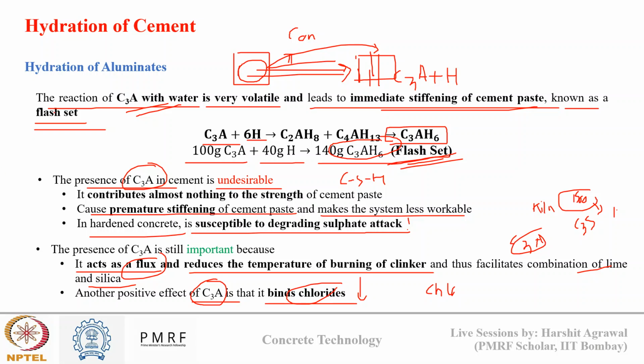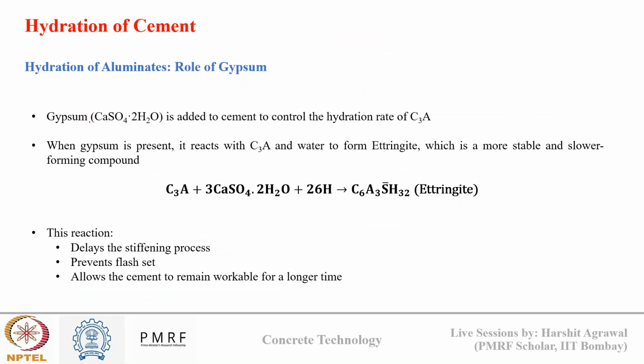Now, how can we prevent this problem of flash setting? To prevent flash setting in concrete, and to make concrete pumpable and flowable for a certain period of time, we add gypsum to cement at the end of the clinker production stage. So what happens when we add gypsum? If gypsum is present in cement, it reacts with C3A and water to form ettringite, which is a more stable and slow forming compound.